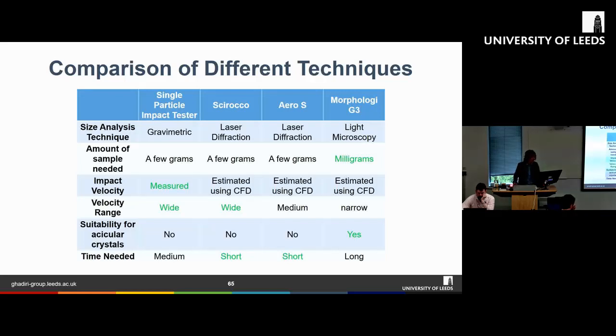And impact velocity, we can measure it, but for the other three methods, we actually estimate it using CFD. The velocity range for the single particle tester can go up to a very high impact velocity. The same goes for Sirocco, but for Aero S, it's slightly lower. But for Morphologi G3, because of the limitations of the gap between the dispersion spool, we can't accelerate the particles to a very high impact velocity.